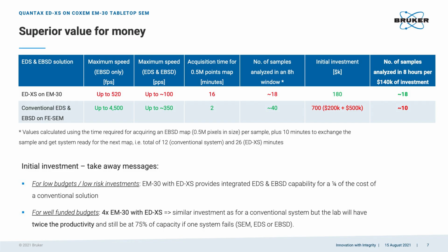But now, if we consider the cost of each of these systems, so if you normalize by the cost factor, then ED-XS is at least 4 times, so it's a quarter of the initial investment. And then if you normalize by that, then you actually, per dollar invested, you are more productive than when you have a conventional CMOS EBSD detector. And you have almost twice the productivity.